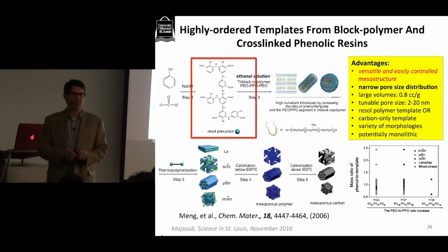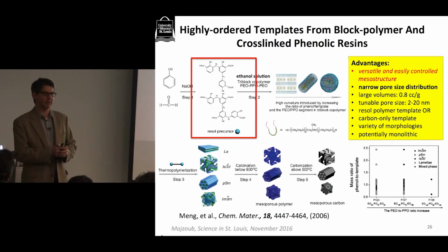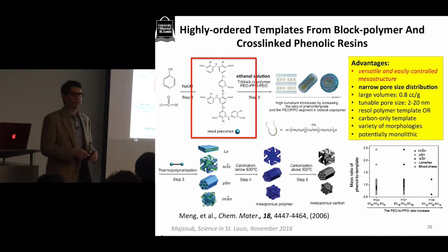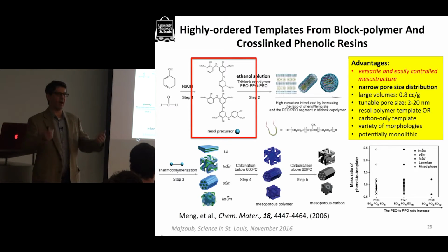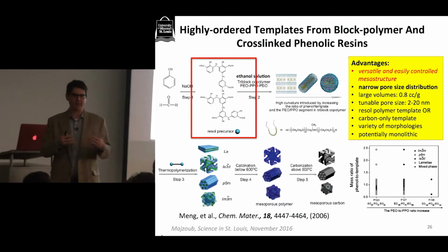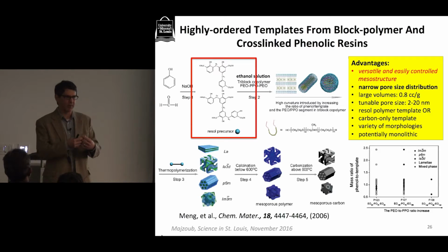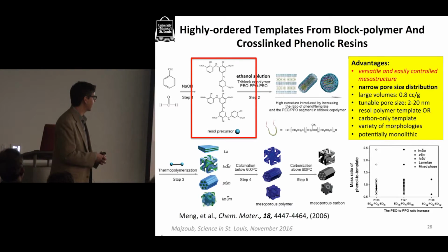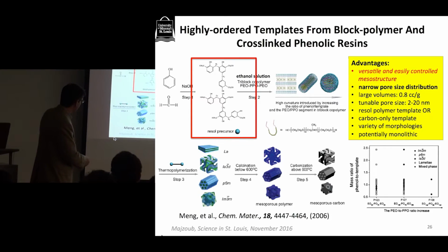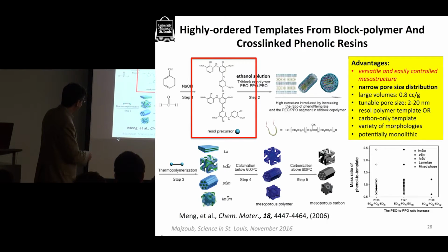And so when we mix these materials together, we do it in an ethanol bath. So this is just an alcohol bath. They mix, and then when we dry the material, we just evaporate the ethanol off. These materials, they'll segregate, sort of like oil and water likes to segregate, except they'll do it on a very, very small scale, and they'll do it on the nanoscale, in fact. And so what one is left with here is a composite that has a nanostructure.